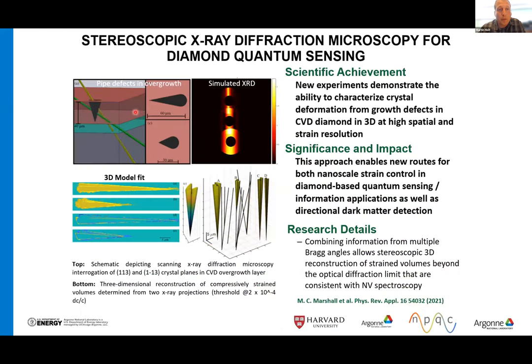Okay, cool. And we can also look at multiple Bragg projections of the same defect to create a virtual stereoscopic view. And this is a very cheap way of doing three-dimensional images because a Bragg diffraction is, of course, relatively sparse in angle. But for modelable defects like pipe defects, it's really quite good that we can look at these defect structures to about 20 to 50 nanometer precision within about a 5 micron cubed volume. And this lets us understand defects used for quantum imaging.